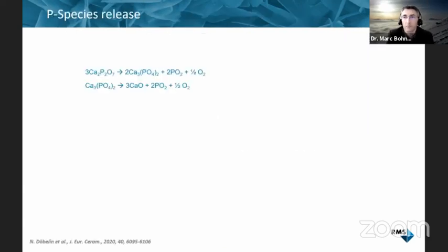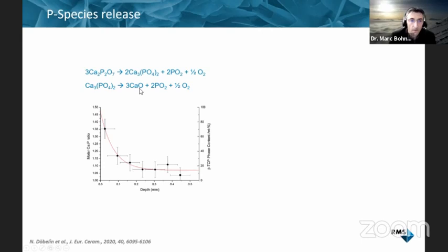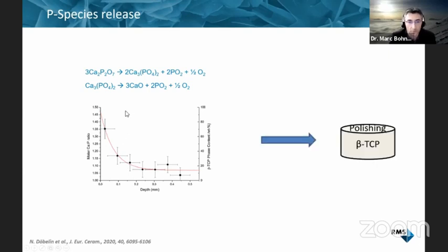Then another problem we have is that calcium phosphates evaporate during sintering. They release phosphor species, and if you start with pyrophosphate, you form a bit of beta-TCP on the surface. And if you start with beta-TCP, you form calcium oxide on the surface. And so sometimes these layers can be quite large. For example, with the pyrophosphate, you get up to 200 micrometers in thickness, where you have a different composition on the surface than in the bulk.